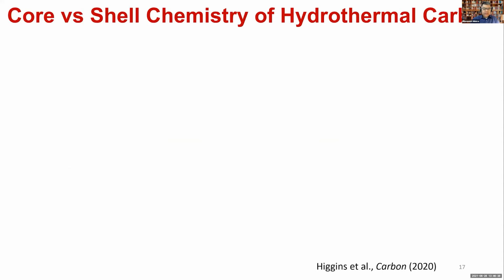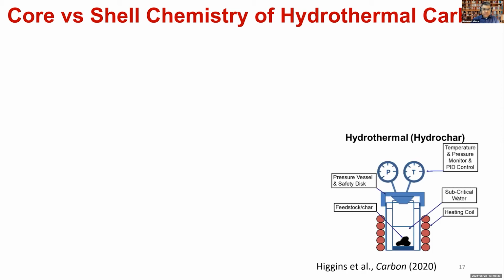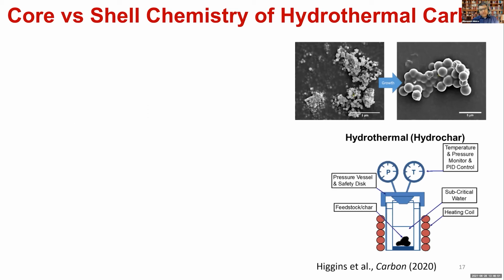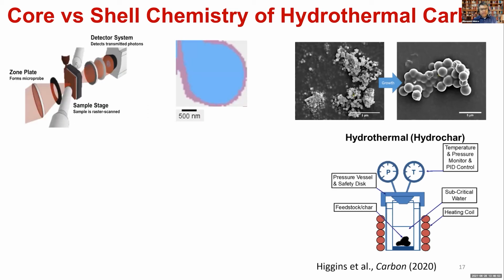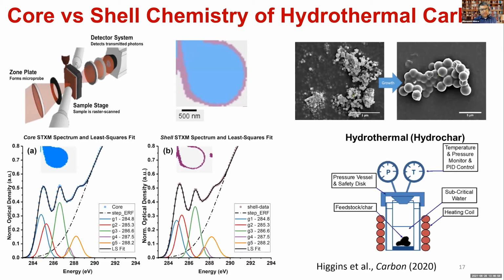So not only that, when we further did STXM analysis of the hydrothermal carbon by again doing FIB sectioning of that, as in focused ion beam sectioning, we could show the core versus shell model of this, which is something that was suspected for a long time, but was never proven, because what happens is that if you conduct XPS on this material, and there are smart ways of removing the upper surfaces in the shell material and then just measuring the core and so on.